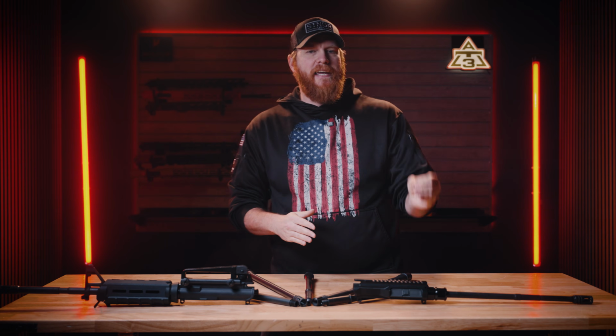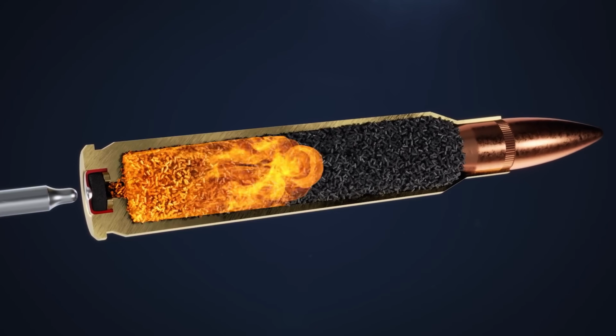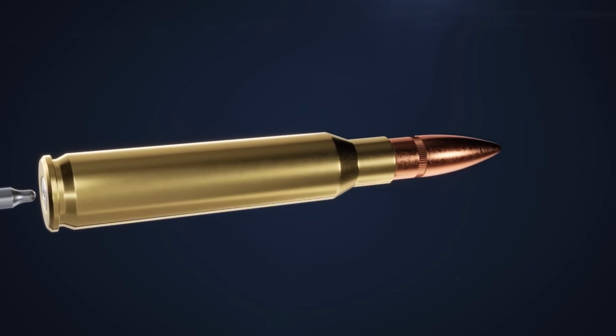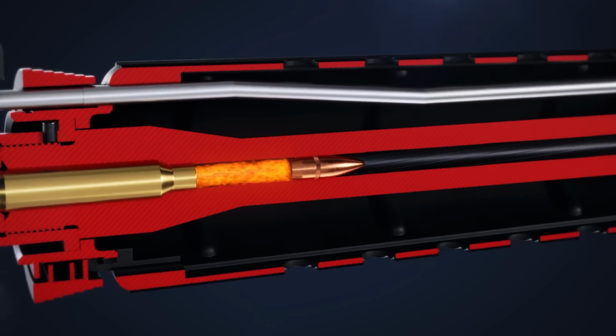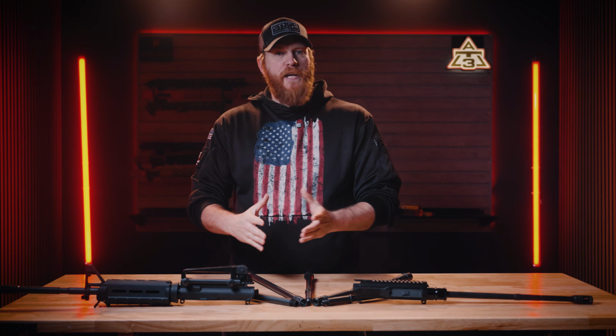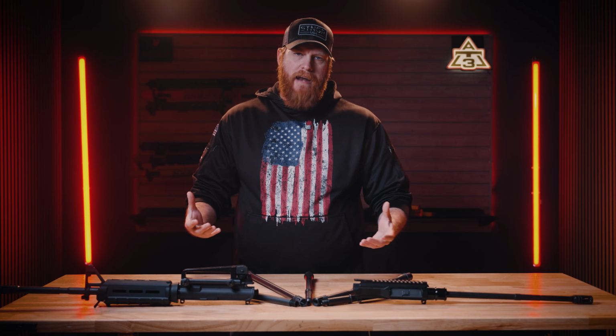We're talking about repeated instances of pressures up to 55,000 to 62,000 psi with constant heat reaching in excess of 500 to 800 degrees Fahrenheit, all while a projectile is scraping its way down the rifling inside of your barrel at 3,000 feet per second. To prevent rupturing, warping, or just plain rapid degradation of the barrel itself, manufacturers have to rely on specialized steel alloys when making their barrels.